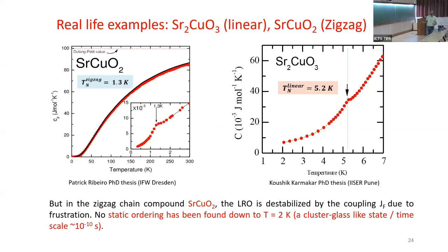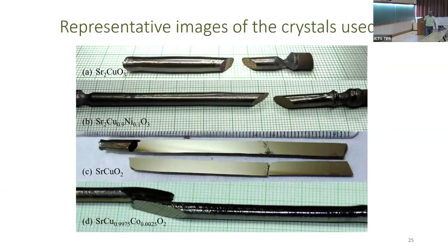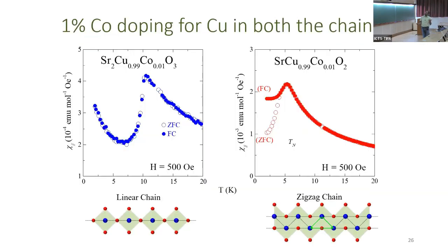And in the case of 213, the ordering temperature is 5.2, which is much higher compared to the magnetic ordering temperature for the zigzag. And this suppression relative to the linear chain is because of the JF. Now, if you're not convinced, by the way, these are the crystals that we have grown in our lab to probe these materials by the float zone method. So this becomes more apparent when you dope just 1% of cobalt in these chains. By doping 1% cobalt, you're just amplifying this effect. Why this effect is getting amplified is something that we will discuss over the next few slides.